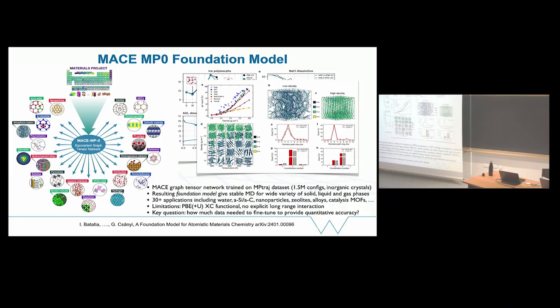So looking at different densities and temperatures, things are coming out in very good agreement with DFT. I would say unreasonably good agreement with DFT, showing the model is really extrapolating across chemical space. It isn't just reproducing what was put into it. Okay, it was only done with PBE, and there was some plus U in some cases, and there was no explicit long-range interaction, as I mentioned.